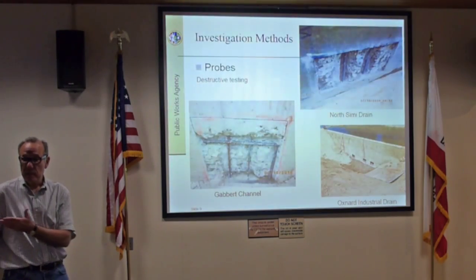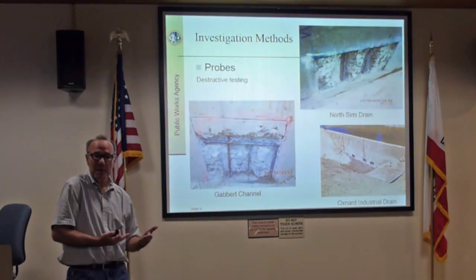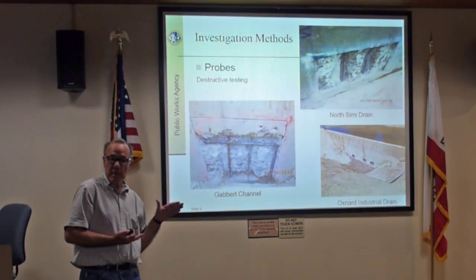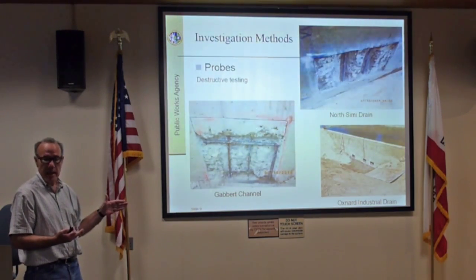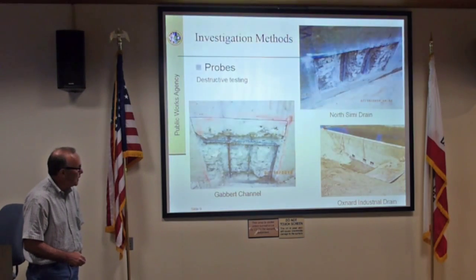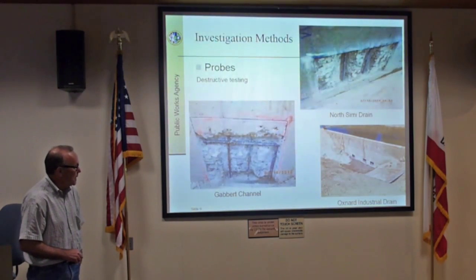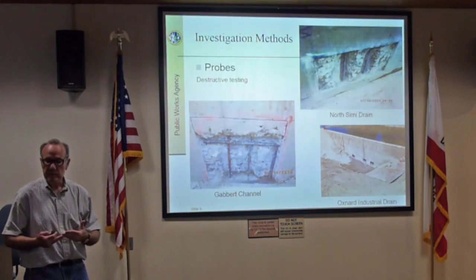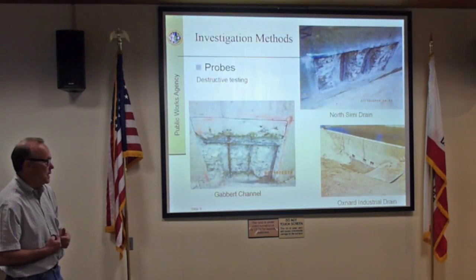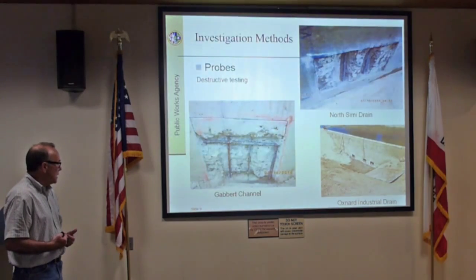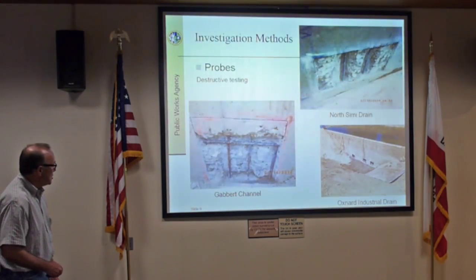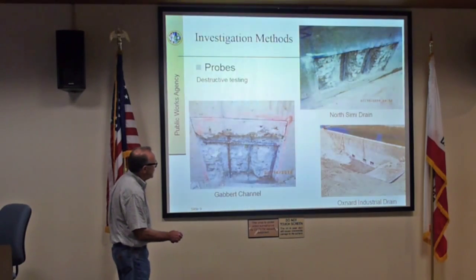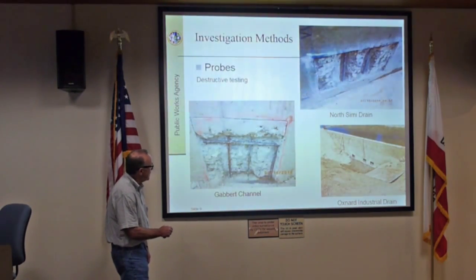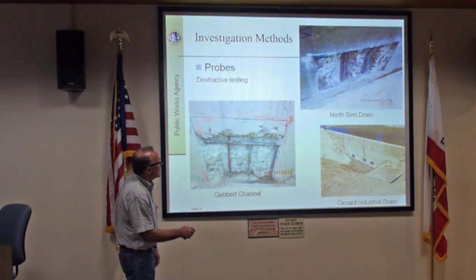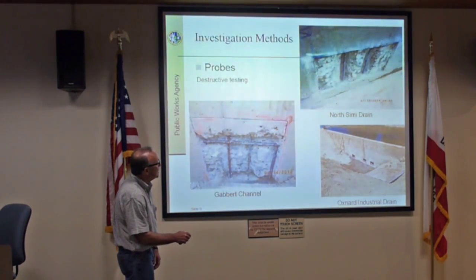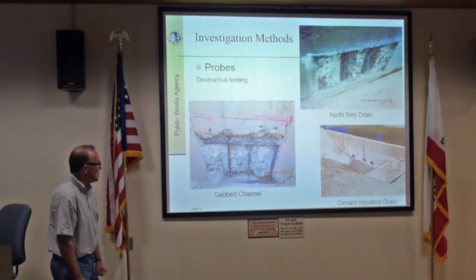The steel of interest, though, is really not the side that we're looking at on the channel. Some of that was single reinforcement towards the backside, so we go to the trouble of looking at that backside, where the reinforcing steel is closest to the water and moisture ingress. You can see here we've got different conditions. The bar looks fairly clean here, but you can see some corrosion product here. Same here, these bars look fairly clean, like there's not much corrosion activity.